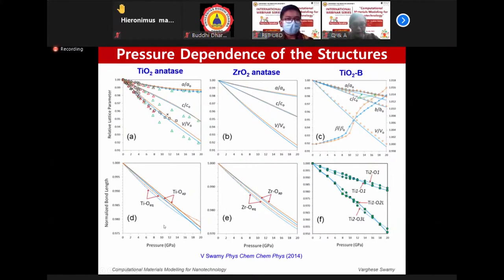And if you pay attention to the bonds I was talking about, the TiO apical bond that is parallel to C, the vertical axis, you can see that it evolves and finally becomes more compliant compared to the TiO equatorial bond. So there's a bond crossover happening somewhere around 14 gigapascals, according to the calculation. But you don't see a similar picture in the case of zirconium oxide anatase.